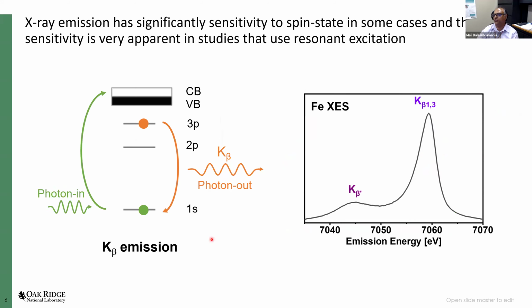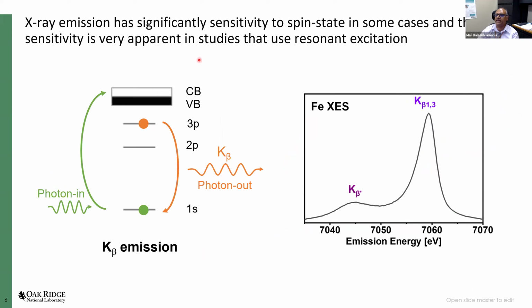So just to give a quick overview, I just mentioned that X-ray emission has significant sensitivity to spin states in some cases. In an X-ray emission experiment, you take a 1s electron and you excite it to an unoccupied state above the Fermi level. This can be done either resonantly or non-resonantly. And after the absorption process takes place, the system relaxes back to the ground state by emitting various photons or losing energy through Auger processes and other methods.